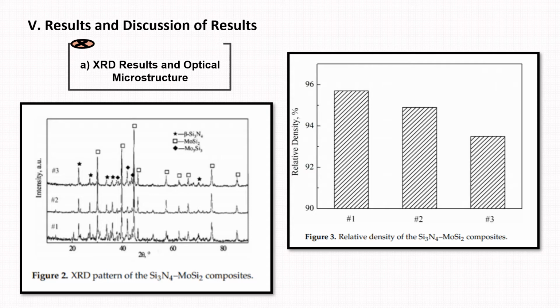Based on this result, it can be claimed that during the hot pressing process, the original alpha silicon nitride changed to beta silicon nitride. The sintering additives, yttrium oxide and lanthanum oxide, reacted with the silicon and oxygen content and formed an amorphous glassy phase. In addition, small amounts of molybdenum silicide phase can also be detected. The figure on the right shows the densities of the prepared samples.